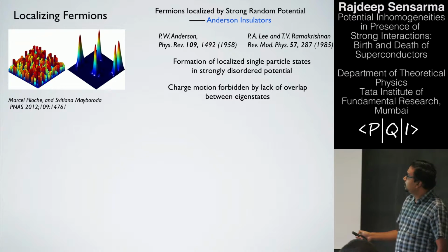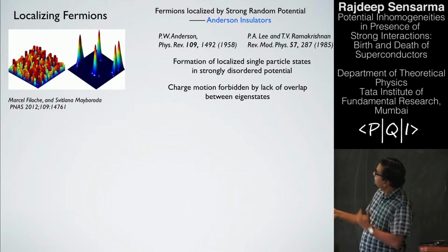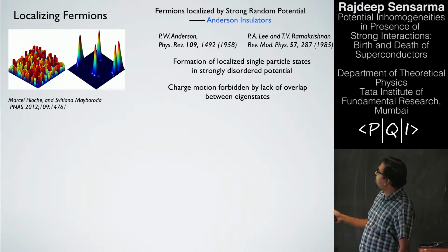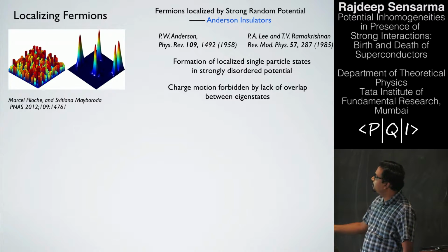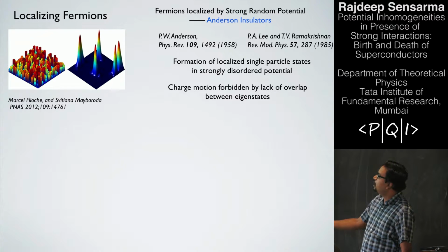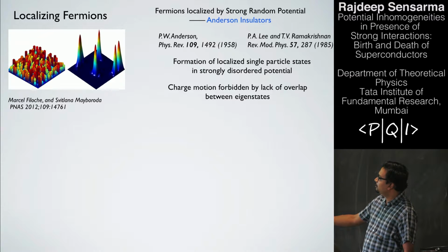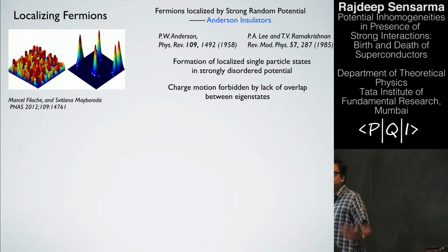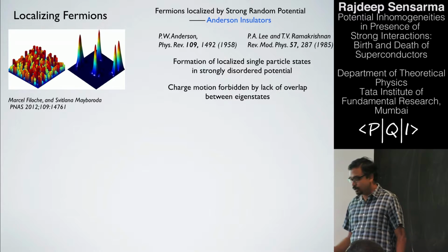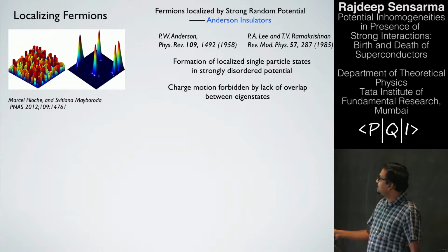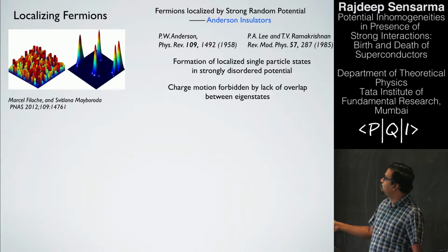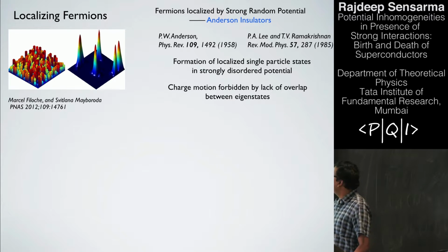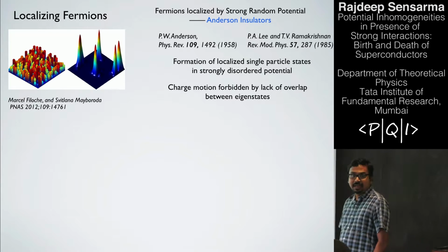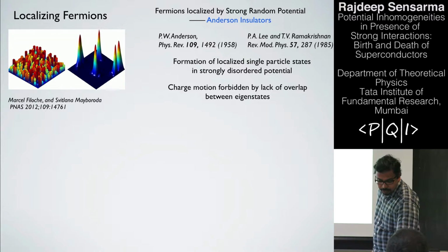But there's more. You can do random potentials, disorder. Electrons can be localized by strong random potentials. What you have here is one realization of a disorder potential on a square lattice, and these are the lowest 5 eigenstates drawn by diagonalizing that whole problem. You can see that they are very localized in real space. They don't overlap with each other much, and hence the charge motion is forbidden by the lack of overlap between these localized eigenstates.